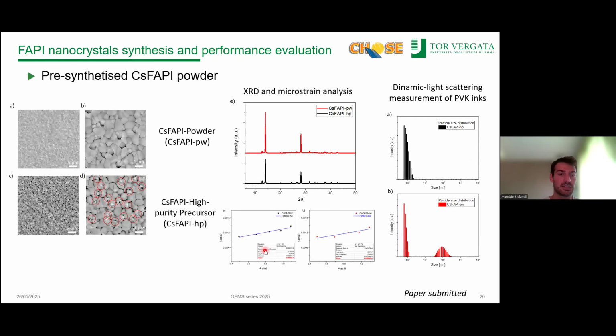So we studied a little bit the film that comes from this FAPI powder precursor solution, and our control in this case is the cesium FAPI from high purity precursors. What we saw morphologically is that the films made from the FAPI powder have fewer pinholes and no unreacted species like the lead iodide that we can see in the high purity precursor case, and also the grains are much bigger. This trend is also confirmed by XRD analysis, which shows higher crystallinity for the perovskite peak at 14 degrees, and the microstrain analysis that we did from the XRD shows less strain in our perovskite lattice for the perovskite that comes from the powder method.